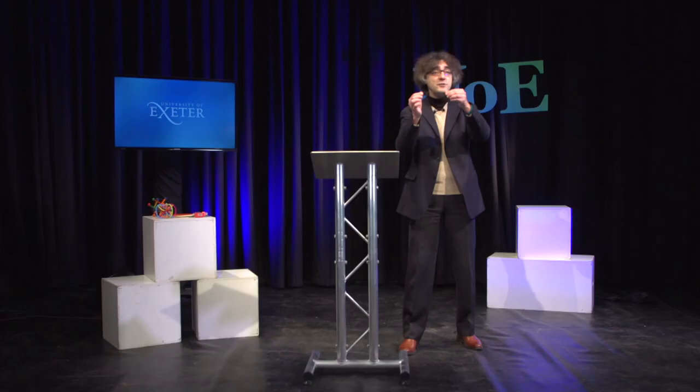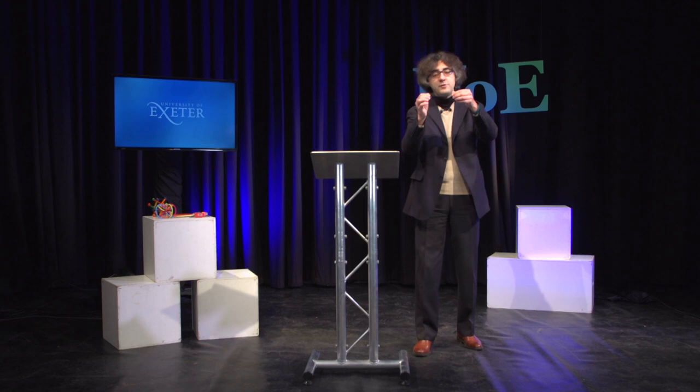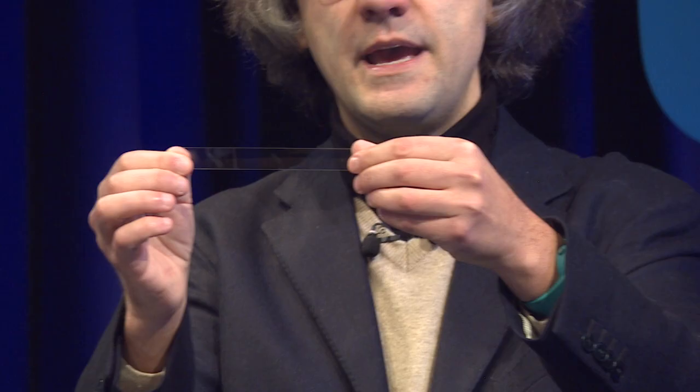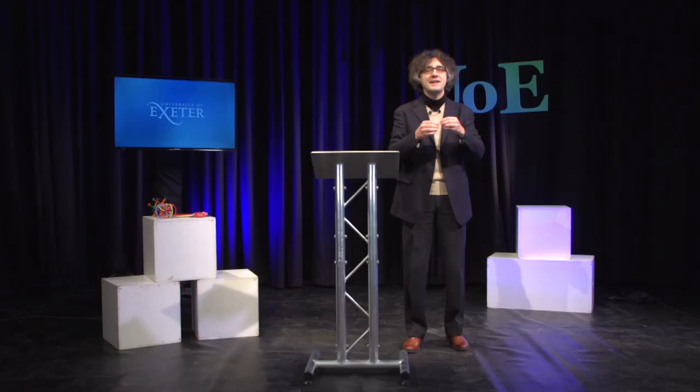You peel off your scotch tape, attach your pencil to the scotch tape and peel it off. If you do it at home, you'll notice there's a grey flake on the scotch tape. Now that's far from being graphene — it's a thick three-dimensional brick of graphite. If you want to go from this to something thinner, you stick the scotch tape to itself, open it into two, and you'll have two flakes each thinner than the first. You repeat this process — open into two, get thinner flakes — and then you hire plenty of PhDs and postdocs and let them do this for many years until you find something that is only one atom thick.